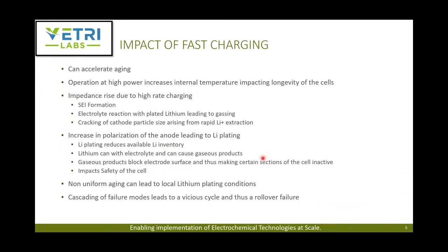What does this do to the actual lithium-ion batteries? This can accelerate aging for multiple reasons. One factor is the internal heating. As we all know, when we do fast charging, our current is very high. The internal heating is related to I squared R, proportional to the square of the current, so it increases the internal heating and the temperature rises, and this leads to shorter cell life by accelerating the aging mechanisms. And what are those aging mechanisms?